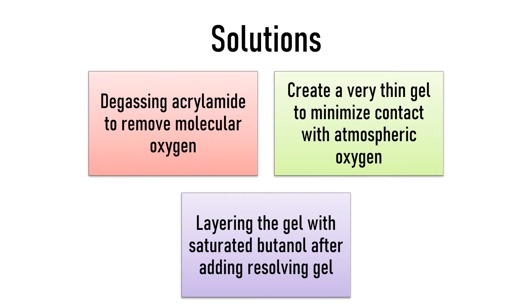To overcome this problem, several solutions are implemented. The first is to degas acrylamide to remove molecular oxygen. Also, to avoid contact with atmospheric oxygen, the gels are created in a thin compartment. After adding the resolving gel, a layer of saturated butanol is added to avoid unnecessary air bubbles and obtain a smooth gel layer.